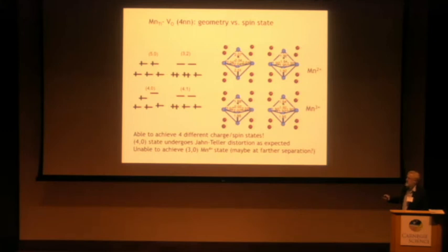So in this case, it happens to have a short axis, but the other ones, in any case, depending on the spin state, you definitely have noticeable changes in the distances between manganese and oxygen. And also, if you see how many spins go into here, you can have manganese 2+ or manganese 3+. In the case where you have the 3+ state of manganese, the extra electron goes into the titanium-oxygen conduction band, kind of. So we tried really hard to see if we can get the manganese to stabilize in the 4+ state like it does for a simple substitution, but we were not successful.